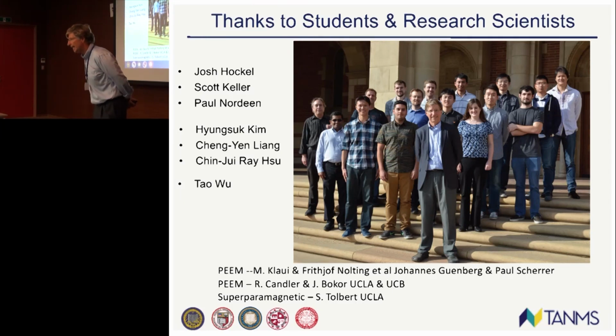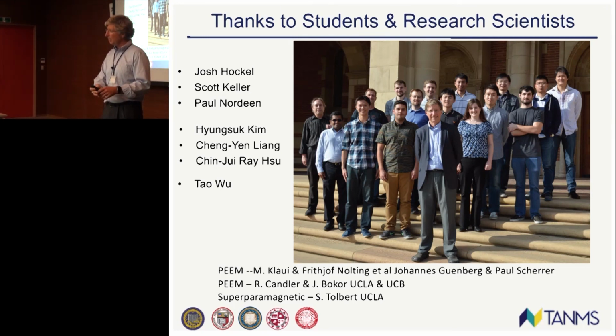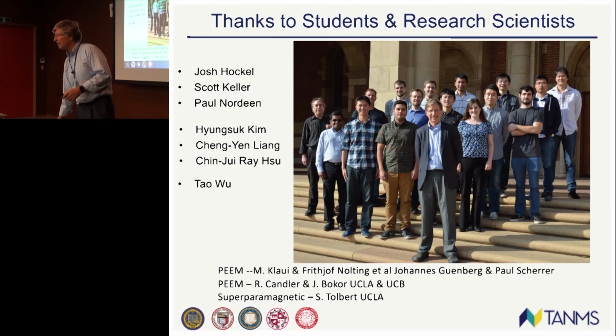We like Terfenol-D and even the terbium iron 2 class of family because they have the largest magnetoelastic properties. We like CoFeB because if we want to look at things at the small scale, we can actually use an MTJ junction. But Terfenol-D and terbium iron 2 have better efficiencies than CoFeB. The problem with Terfenol-D and terbium iron 2 is, let's say you go talk to the memory guys, well, can you read it with an MTJ? There are a few papers out there on using that as an MTJ, but nothing to the magnitude that you see with MgO and CoFeB. So I would prefer working on other things besides CoFeB and MgO, but to see what we want to see at 100 nanometer length scales, CoFeB and MgO make an ideal test platform.